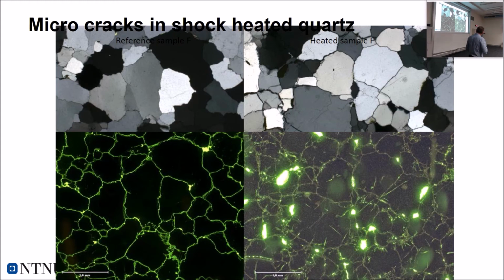And internally in each grain you have small microcracks and also some inter-grain cracks across grain boundaries, so the entire rock mass is fractured, which is showing that this is not just fractured a little bit. When this moves down into the furnace, the fragments have weakened and will break into finer and more dusty grains on the way through the charge, which is 5, 6, 10 meters high, and create more fines as it moves down.